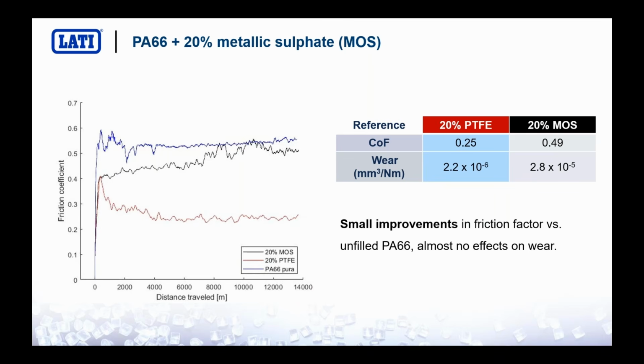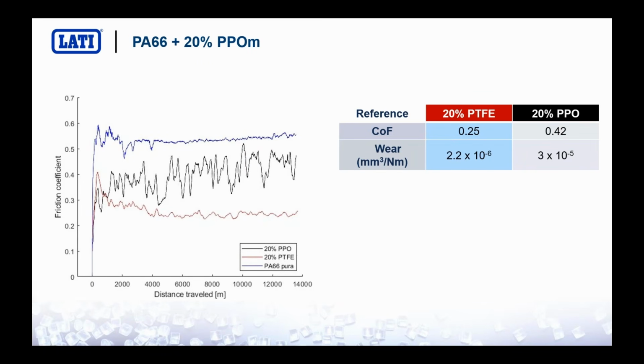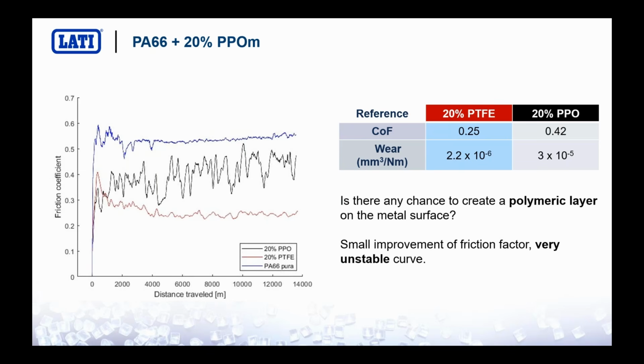Then we tried to test other polymers to take advantage of a possible film transfer effect, like for example PPO, which is a polymer used also as base polymer in injection molding. As you can see, the behavior is really strange. It shows a very unstable curve. It seems that the film was created just for a while and then was broken and then recreated another time. The average of the friction coefficient is lower than the polyamide 66, but for what concerned the wear resistance, we didn't see any advantages compared to the unfilled polyamide 66.